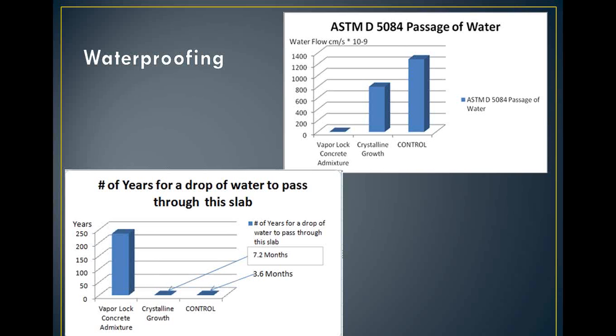You talk about waterproofing, keeping things out of the concrete. This is the Vapor Lock Concrete Admixture. This is a crystalline growth formula. It took 250 years for moisture to pass through this test sample, and it took 7.2 months there and 3.6 months against the control. So they certainly are doubling the waterproofing capacity, but nowhere near impermeability.